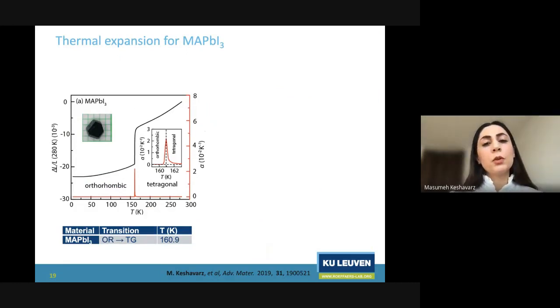Now let's take one of the best-known crystals, methylammonium lead iodide, in which the transition temperatures are known in the literature, and see if our technique can access such transitions. In this plot, you see delta L over L as a function of temperature, and on the right axis, the derivative of delta L over L, which is just the thermal expansion coefficient. Any abrupt change in delta L over L as a function of temperature can be an indication of a structural phase transition.